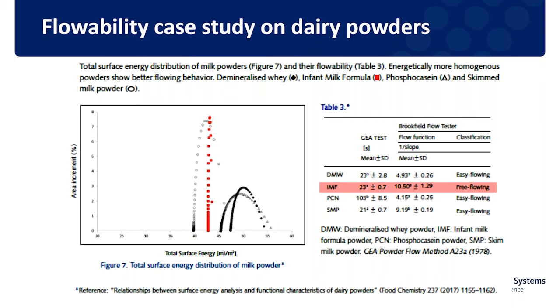And you can see we measured different dairy powders. So we measured the surface energy heterogeneity of these 4 different powders, dairy powders, milk powders. And from the surface energy heterogeneity graph, you can see that this IMF has a very uniform surface energy profile. Compared with the others, it's more uniform. And the flowability test showed that this sample is free flowing.